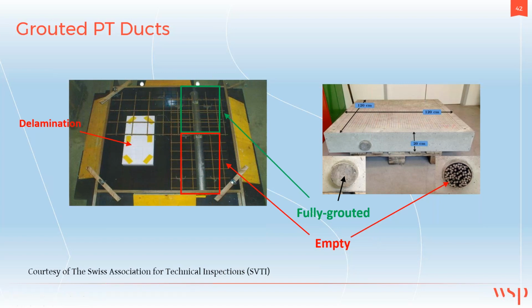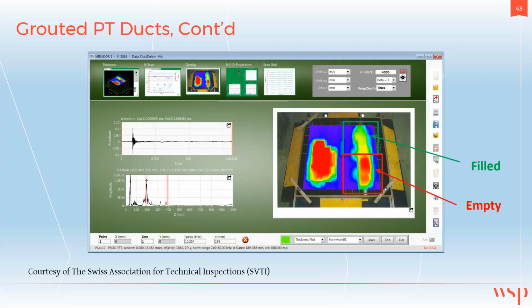They tested the slab using impact echo on a fine grid, and let's look at the results. As you can see, we get a completely different response where the duct is fully grouted as opposed to where it's empty. You also see that impact echo obviously captured delamination quite well as expected.